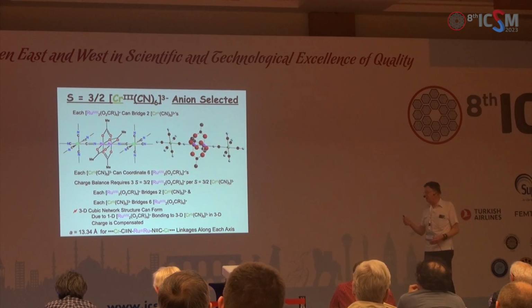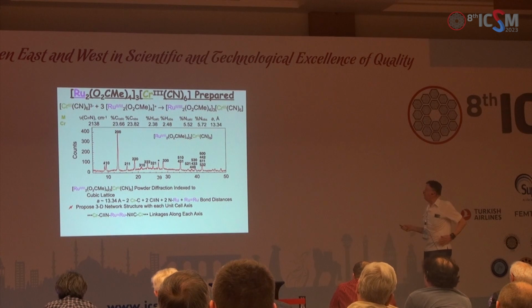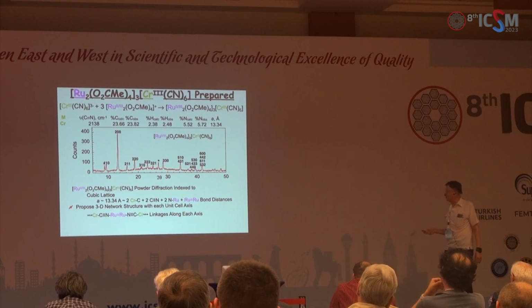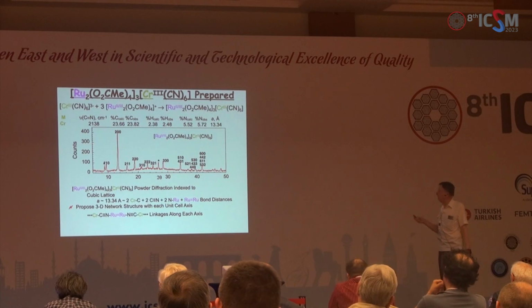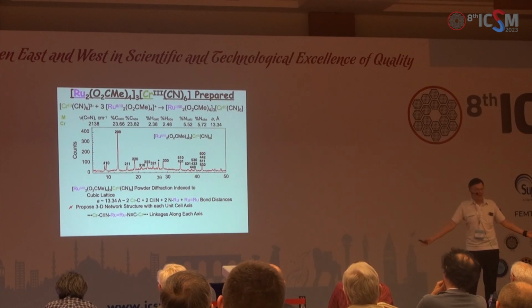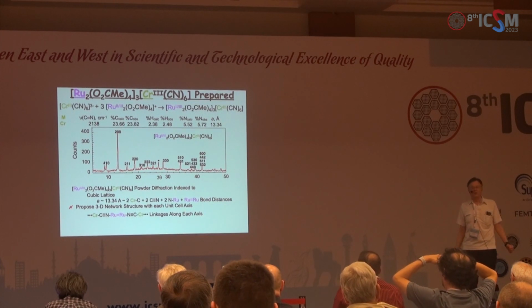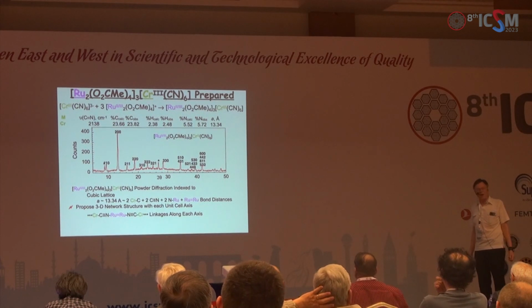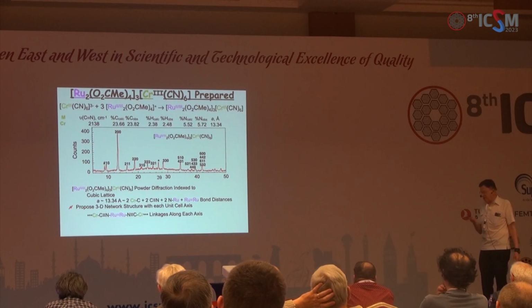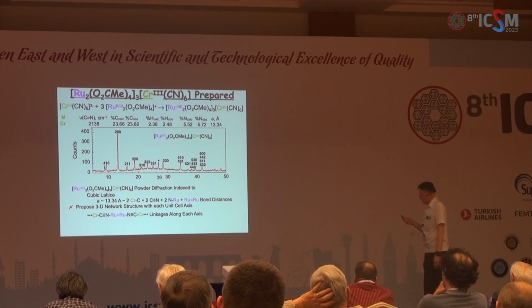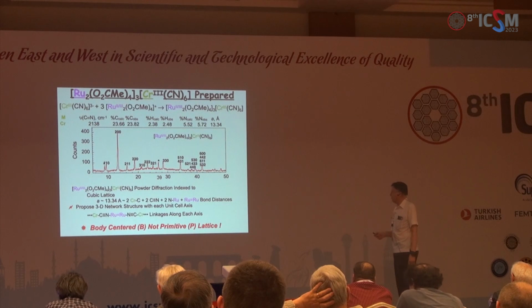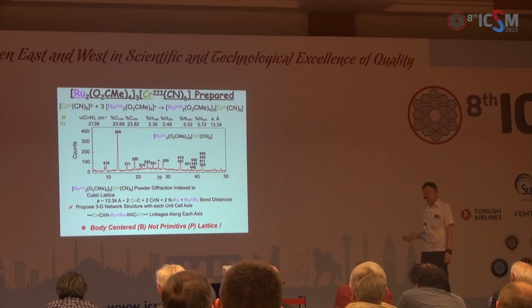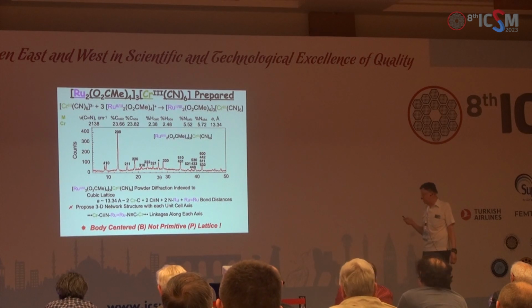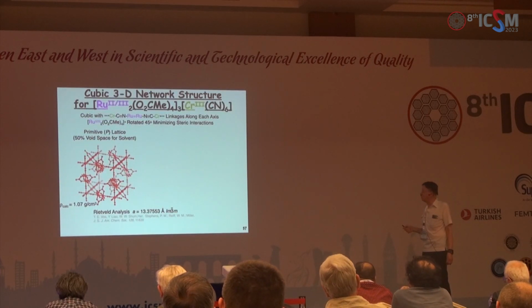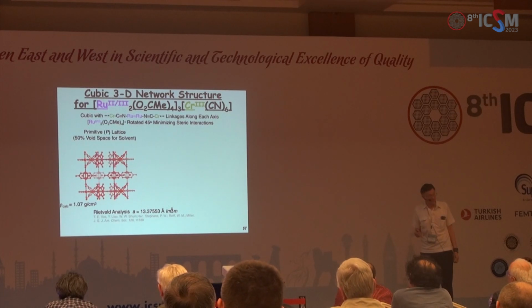We went into the lab and made this, and in fact we got perfect elemental analysis and powder diffraction data telling you it's a cube with a value of 13 and a third angstroms. We designed it, it came, but there was a little surprise—and I'm sure someone in the audience has picked up on it—that's not the powder pattern of a primitive cubic lattice, that's a powder pattern of a body-centered cube, not a primitive one.